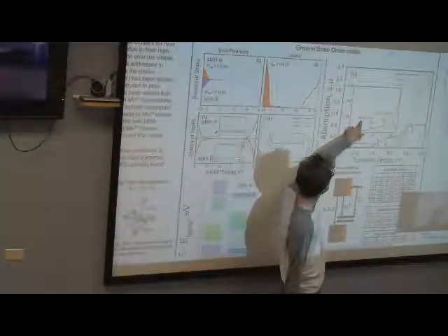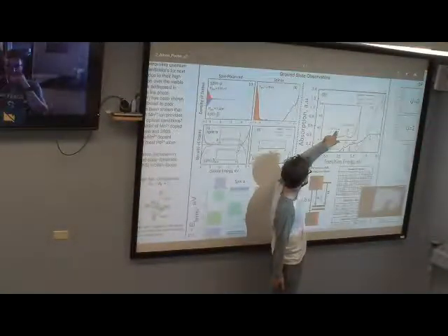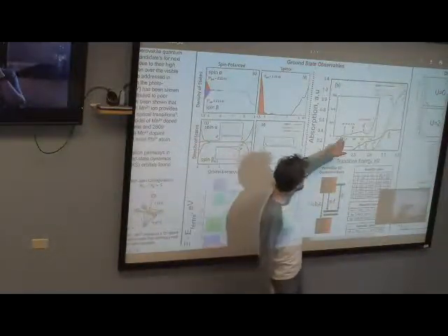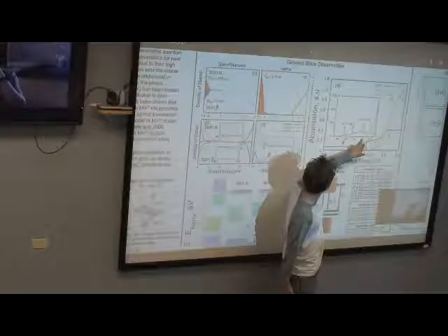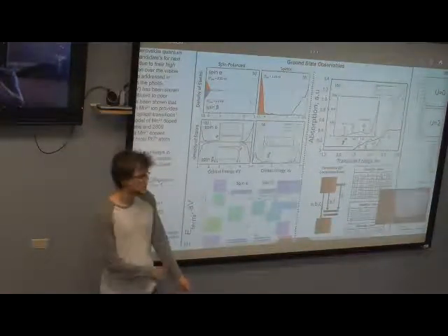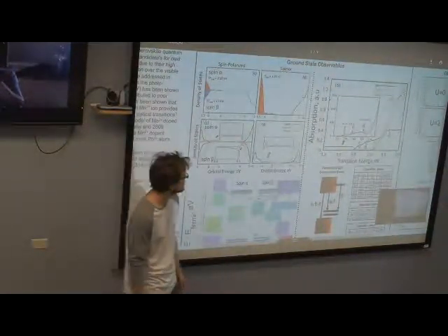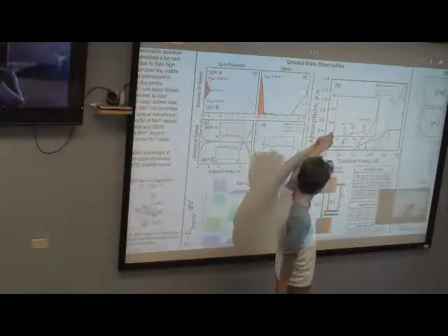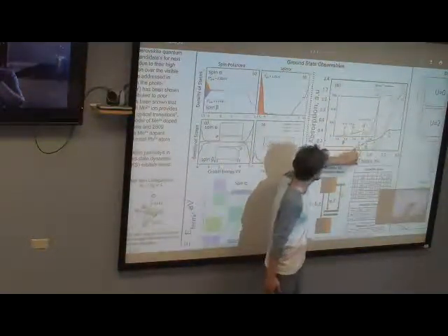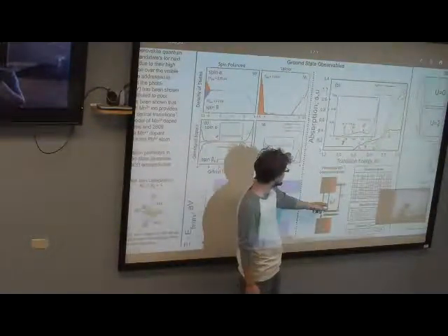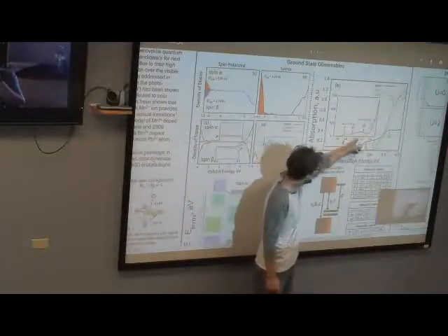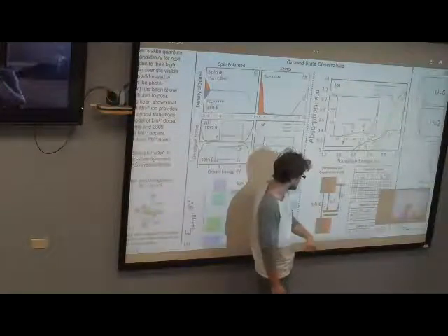we see the lowest two bands are Mn 3d to lead 6p transitions, and that's confirmed from looking at partial density of states. And then once we get up to around 2.2 eV, we do see D to D optical transitions computed from the transition dipoles from the spinors. Then this diagram corresponds to the absorption spectra, with labels corresponding to the ones in the table. So for E and F, that's from perovskite band edge to Mn D state. And then this D is from Mn D to Mn state.